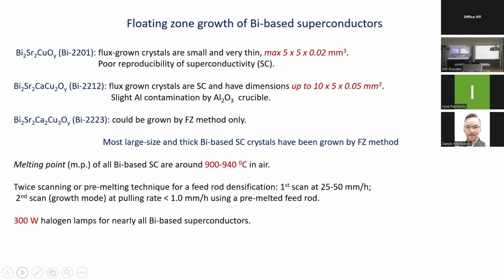So now, floating zone growth of bismuth-based superconductors. It is possible to grow at least these two members of this family by flux, although the thickness along the C-axis is very, very small, tens of micrometers. And bismuth 2223 could be grown by the floating zone method. And nowadays, most large size and thick bismuth-based superconducting crystals are grown by floating zone.